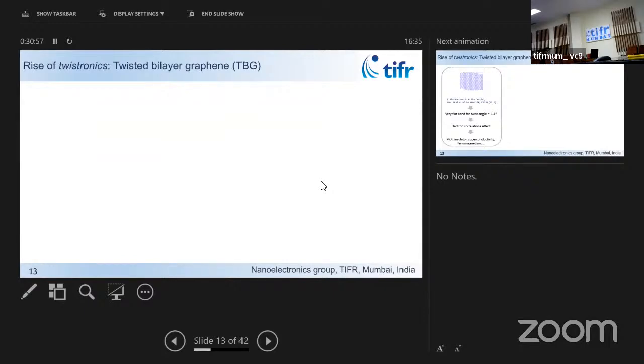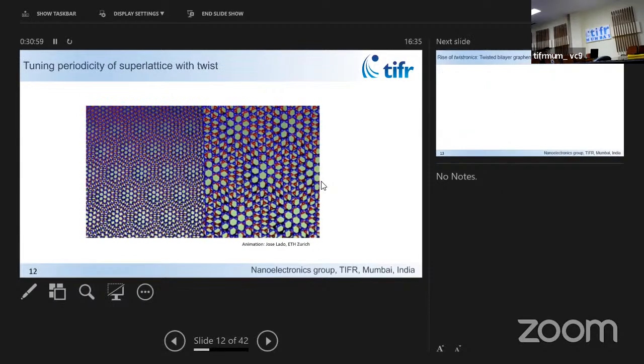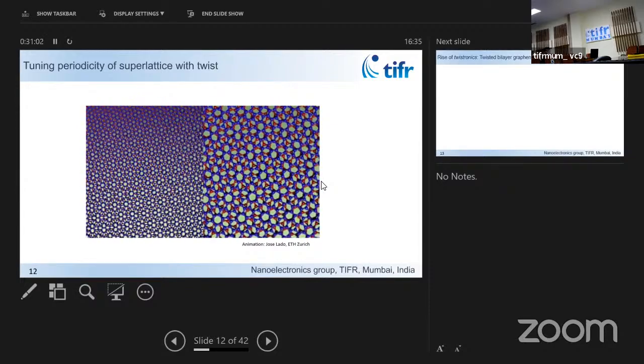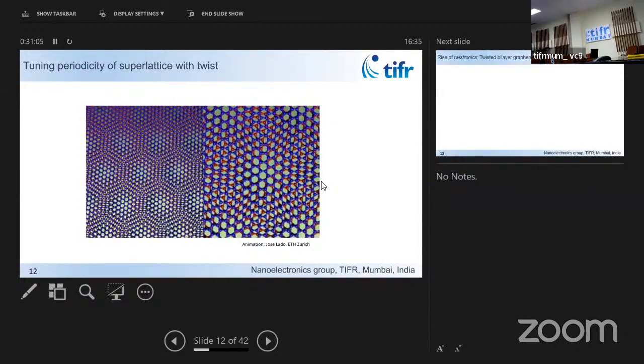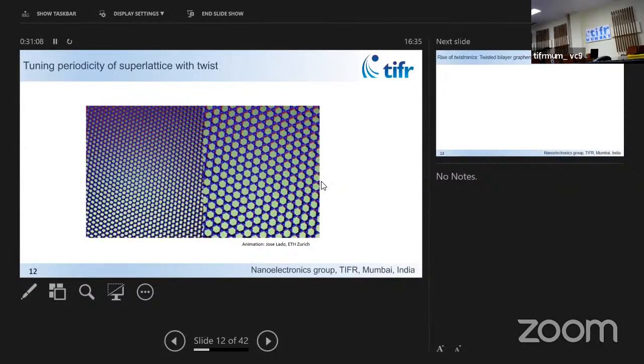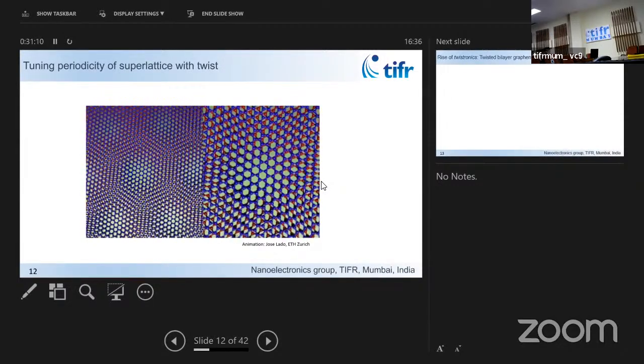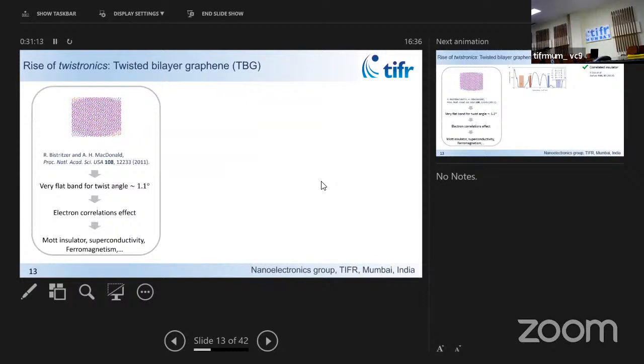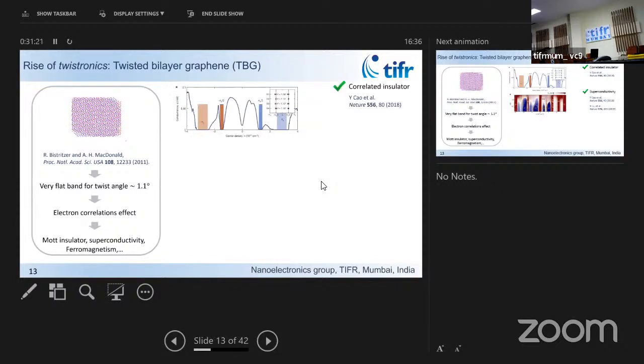So this gives rise to a superlattice. Angles control the periodicity. As you can see in this cartoon, as I change the angle, the length over which the superlattice exists changes, and at a very small angle the periodicity is large. It's inversely proportional to the twist angle. There has been a lot of buzz in this field since roughly 2018, when the first set of papers came out. They're based on some predictions; there were a bunch of different papers, but a lot of work was done by Allan MacDonald and his then postdoc, Rafi Bistritzer.